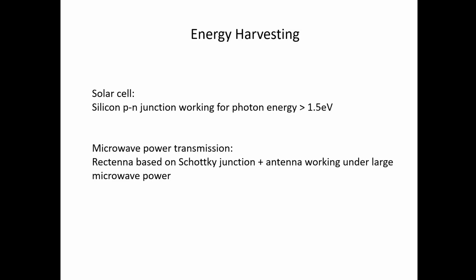Okay. The other possible application is based on energy harvesting. We know that if we can convert high frequency radiation, electromagnetic waves, into DC electric power, this would be useful. For example, solar cells based on silicon PN junctions are widely used already, and they work for photon energies above the band gap, which is 1.5 eV. But there's also a lot of electromagnetic energy at frequencies below this 1.5 eV, and these are wasted. On the other hand, the nonlinear Hall effect I talked about actually works from DC all the way to the terahertz regime, and so this could fill in a gap in solar energy harvesting.